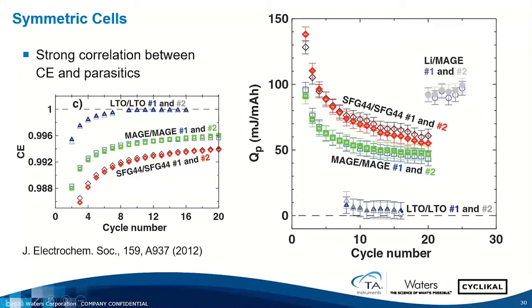Interestingly, the titanate electrode shows almost no thermal parasitics. Very, very difficult to measure. And there's a good reason for that. The titanate electrode has a working potential of about 1.8 volts versus metallic lithium, where the graphite electrodes get down to about 50 to 75 millivolts of metallic lithium. So the reactivity of these materials is very much a function of their operating potential, so being very, very close to metallic lithium, so very, very reducing.